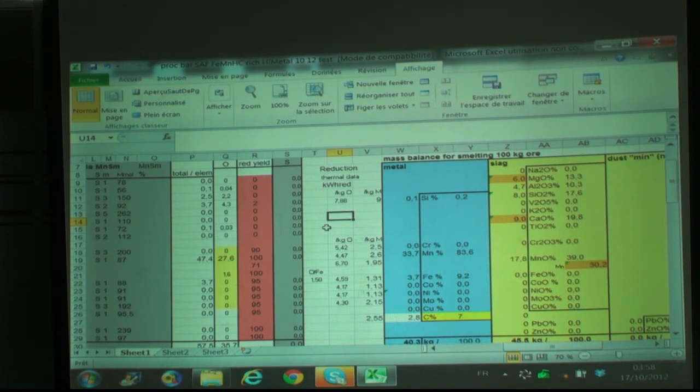So if you have MnO2, it is reduced practically for free, except that you need a bit more energy, but it is not costing more carbon. If we do not use the MnO2 and charge just MnO, the CO gases go outside.